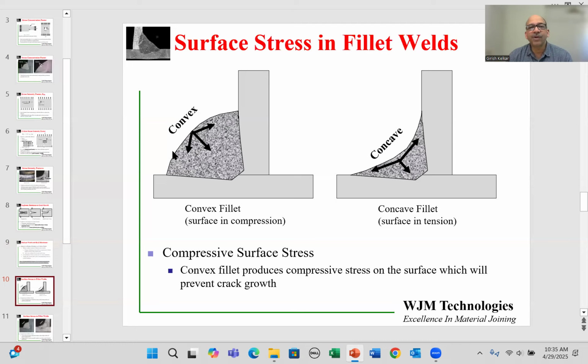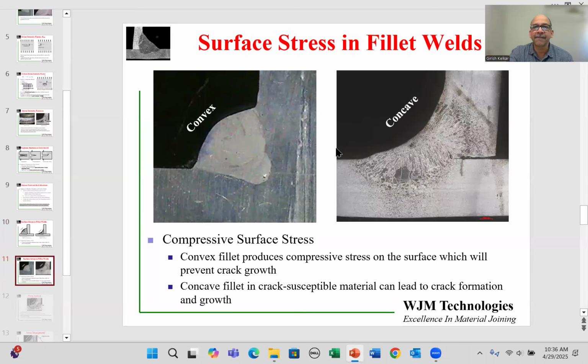So when a fillet weld has a convex profile and that molten metal cools, it tends to shrink inwards, and it is now trying to occupy a smaller volume, and that produces compressive stresses on the surface of the weld. As opposed to that, a concave profile, when it shrinks at the end of the weld, it actually produces tensile stress on the surface. So a concave profile becomes more susceptible to crack growth because if there's a tiny crack on the surface, we already have tensile stress. On top of that, when you are pulling the weld, it adds some more tensile stress, and that can lead to crack growth under certain circumstances.